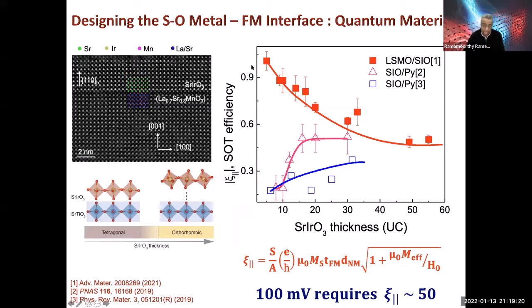So if you see the data here, this is a spin orbit torque efficiency, which is given by this rather complicated looking equation. It's as a function of the strontium iridate thickness. Now, if you look at the epitaxial structure, that's shown in red. And you can see as I make the iridate thinner and thinner, we think there are structural transitions going on and also electronic reconstruction going on at this interface. That efficiency can be as high as 1 to 1.5. On the other hand, if I use the same strontium iridate, but use permalloy as a ferromagnet, no interface epitaxy, you could see that that efficiency is of the order of 0.3. So these epitaxial interfaces can be dramatically different.